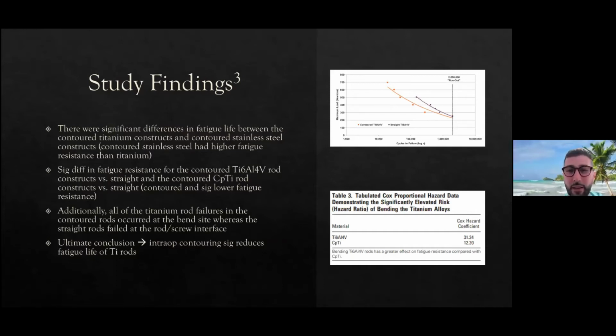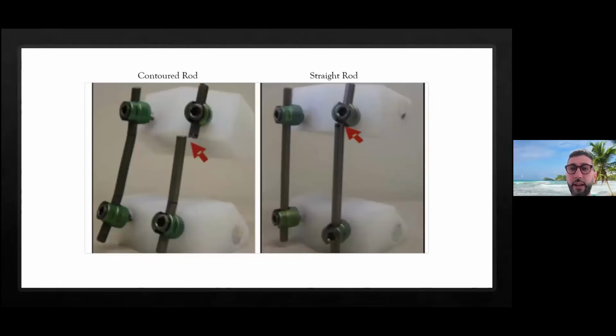And I think the number is about 60% reduction. It's quite significant. Additionally, all the titanium rods failed at the bend site, whereas the straight rods failed at the rod screw interface. So they failed at a higher stress and at the rod screw interface. So the ultimate conclusion here was that intraoperative contouring significantly reduces the fatigue life of titanium rods. And this is just a picture that demonstrates this is a contoured rod. You see it broke at the site of notching, and the straight rod broke at the rod screw interface.